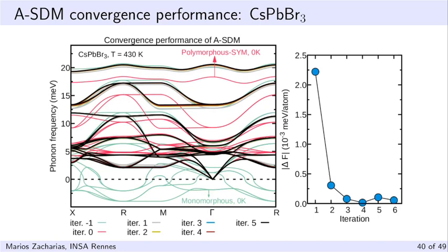If you cannot increase your supercell size, and the best you can do is a 4×4×4, for example, you need to perform the calculation for that particular supercell size, and maybe take an antithetic configuration, which is basically a configuration with the reverse sign for the phonon modes, to see exactly what is the level of error that you have in your calculation. If these two are close to each other, you can simply take the average and get a final result, which I think will be accurate enough.